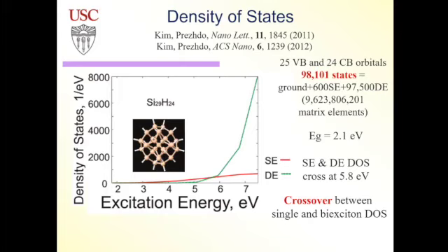So if your bandgap is 3 eV in this case, and you excite at 6 eV or better 7 eV, so you have to go maybe 2.5 bandgaps above. You're gonna create single exciton, and then if you have Coulomb interaction that allows you to exchange energy between particles, then you're gonna go from low density of single excitons to high density of double exciton states by Coulomb interaction. And then what will happen eventually, you're gonna start losing energy to heat, to vibrations.